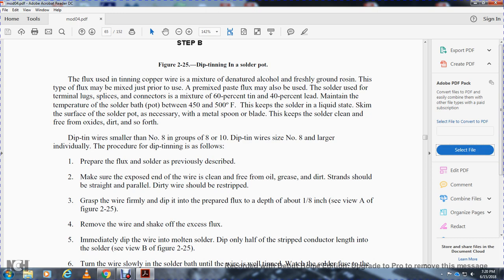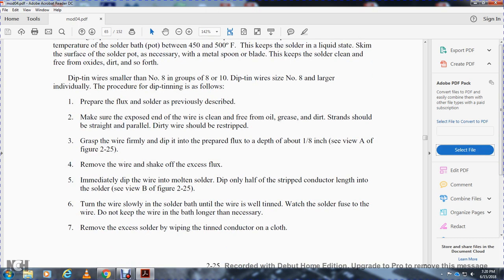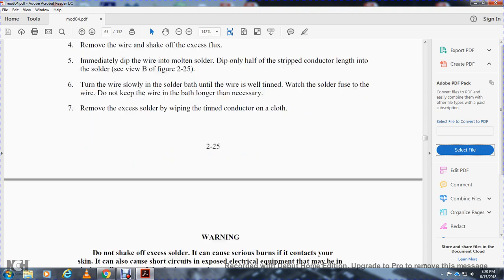Grasp the wire firmly and dip the end into the flux to a depth of 1/8 inch. See view A, figure 2-25. Remove the wire and shake off the excess flux. Immediately dip the wire into the molten solder. Dip only half of the stripped conductor length into the solder, view B of figure 2-25. Turn the wire slowly in the solder bath until the wire is well tinned. Watch the solder fuse to the wire. Do not keep the wire in the bath longer than necessary. Remove excess solder by wiping the tinned conductor on a cloth.